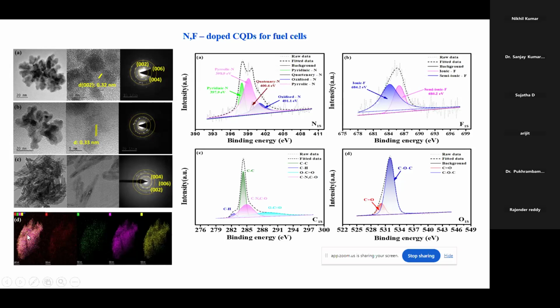So this elemental mapping also shows the presence of the elements, and then this XPS shows the pyridinic and pyrrolic presence, which is having this N. And then this F gets polarized. I already mentioned it gets polarized, so it becomes ionic and semi-ionic. Then the COC, CO bond.